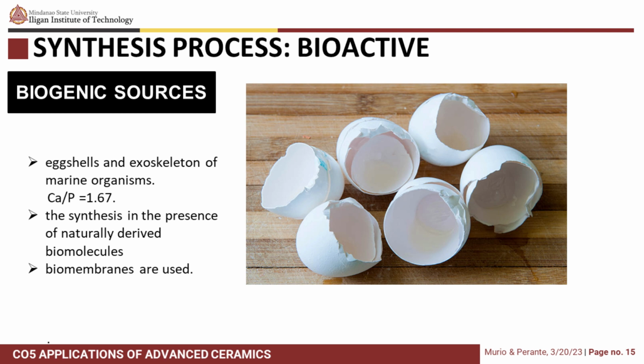The first one uses biogenic reactants from the eggshells and exoskeletons of marine organisms. For example, calcia produced from eggshell via calcination at high temperature is hydrated and reacts with phosphoric acid to precipitate. The calcium and phosphate molar ratio is mainly maintained at 1.67. The second method is the synthesis in the presence of naturally derived biomolecules. There is also the synthesis method in which biomembranes are used.